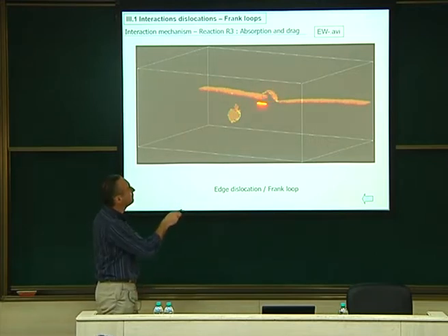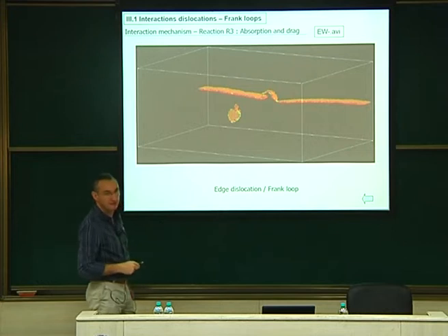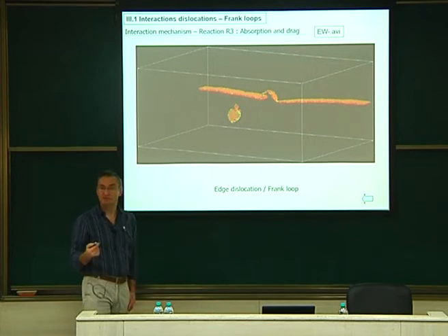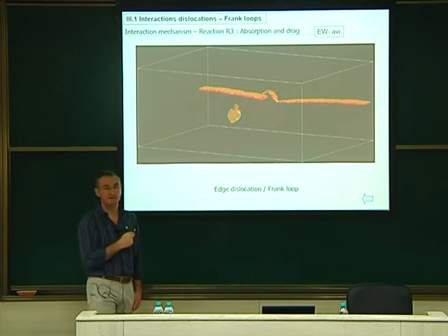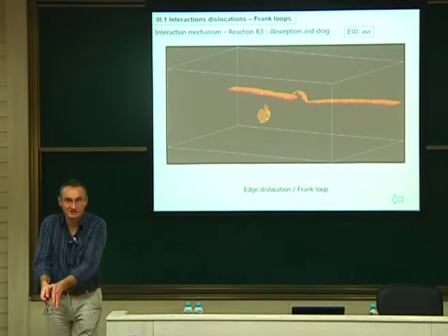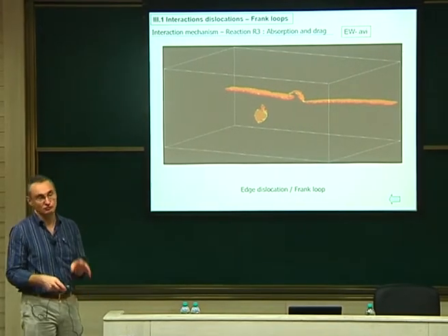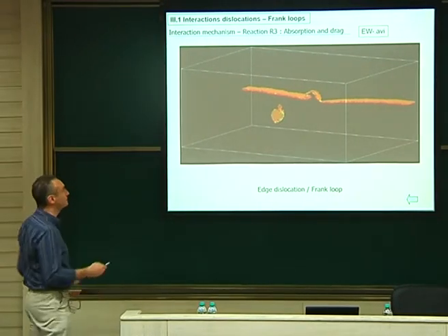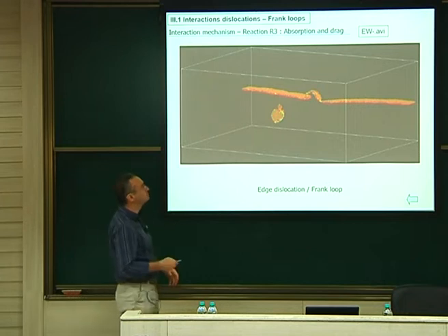Now the dislocation is no more planar. There are some out of plane segments. And part of the loop has been removed. So this is a cleaning process, actually. You have removed part of your defect. As if you are just sweeping your defect a bit, you remove some of it. So you are starting to build a clear band. Very small. You just remove a small part of the loop. But at least it is one possibility to absorb a loop.